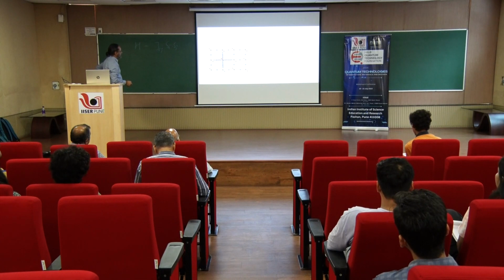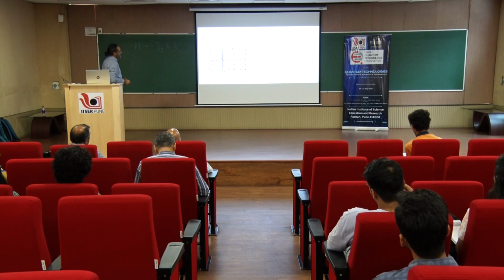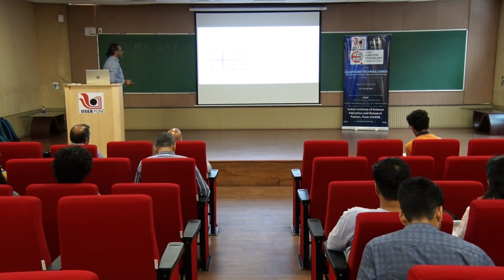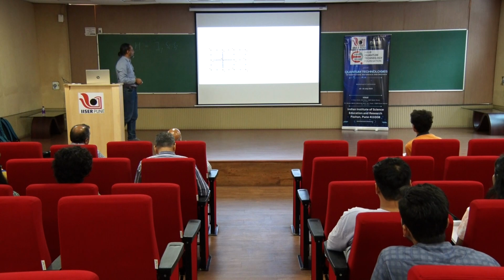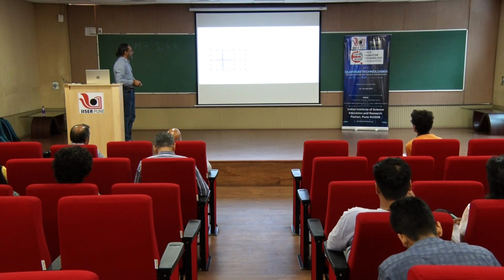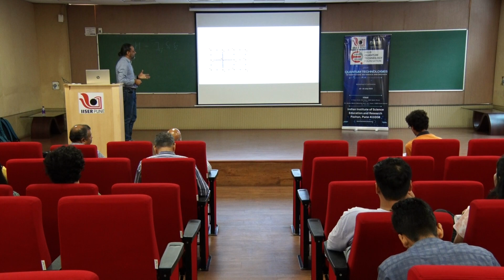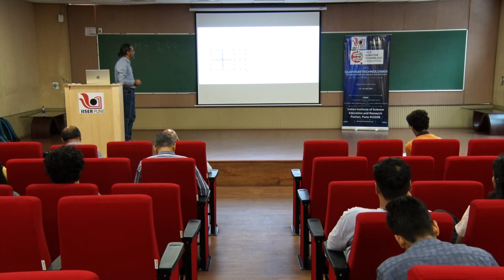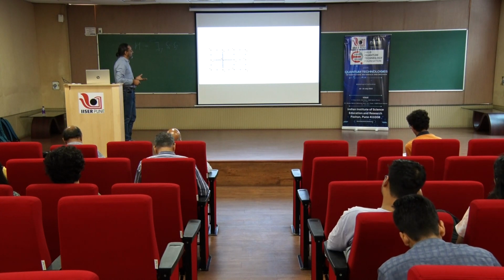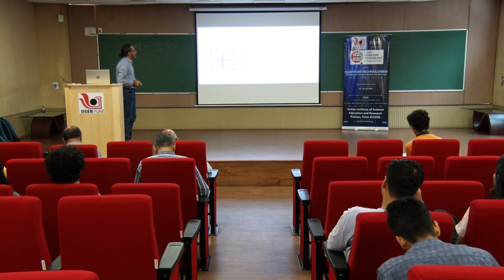So this is basically the Hamiltonian, and what is depicted here is that the x square minus y square orbital has only one electron. That electron is allowed to delocalize only over these nearest neighbor bonds. Okay, so this is known as virtual hopping. What's happening is that the electron, by virtue of this t term, which is not exactly 0, there is some non-zero t, the transition matrix element, and because of that the electron once in a while hops onto the copper and comes back. This is known as virtual hopping.